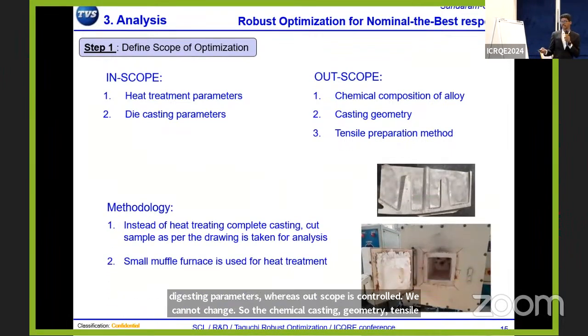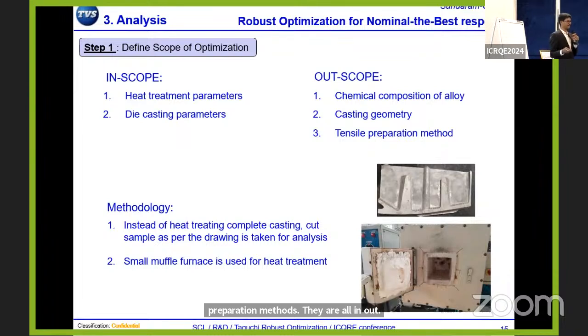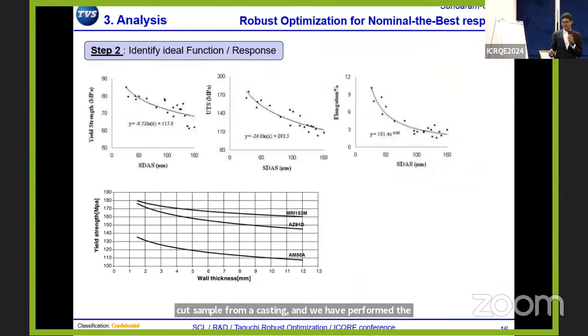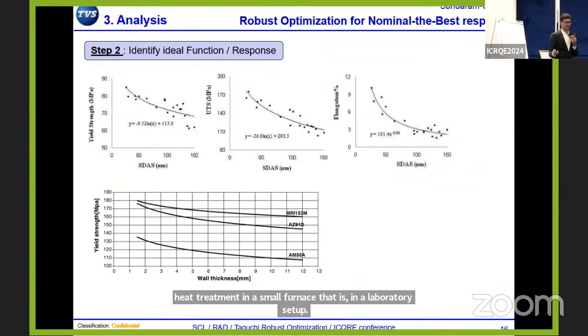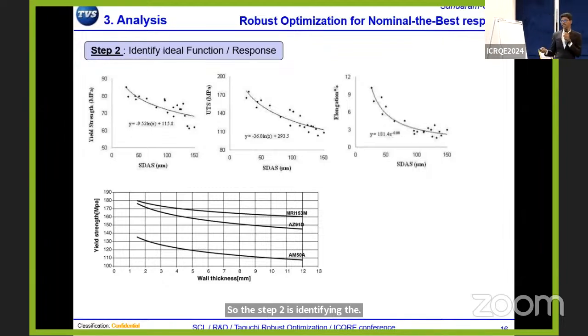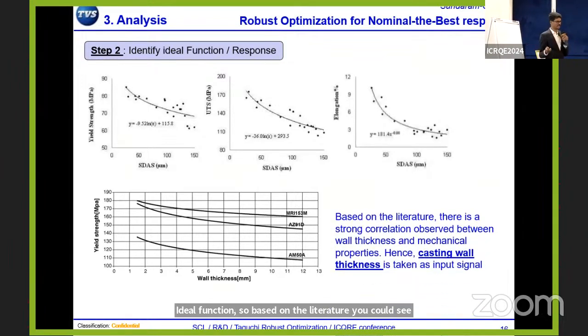Coming to methodology, instead of testing the complete casting, we have taken a cut sample from a casting and performed the heat treatment in a small muffle furnace in a laboratory setup. Step 2 is identifying the ideal function. Based on the literature survey, there is a strong relation between the mechanical properties and the wall thickness of the component. So wall thickness is taken as the input signal.